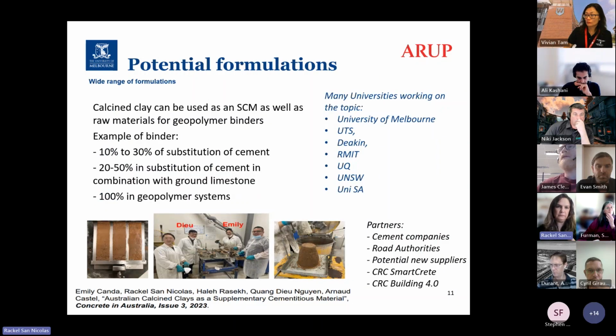So there's a lot of potential formulation using calcined clay. Formulation of concrete, obviously, that's what I'm talking about. And when I say a wide range, it means that calcined clay can be used as substitution of cement, like 10, 20, 30%, just straight substitution by weight, and has great durability performance there. It can be used as well, and I'm sure you heard about what we call LC3, which is a mix basically with calcined clay and limestone. That is the mix of the two substituting cement.